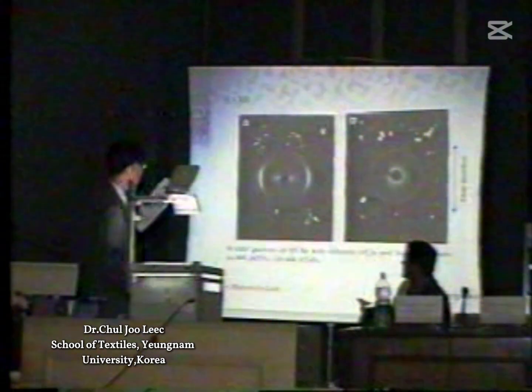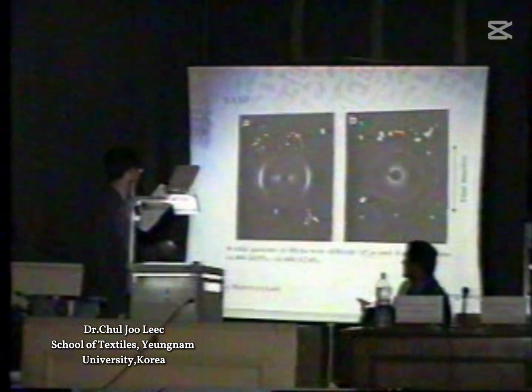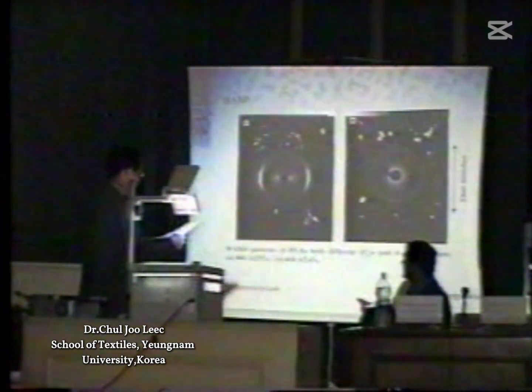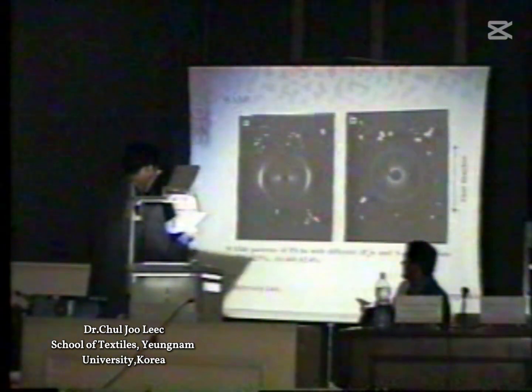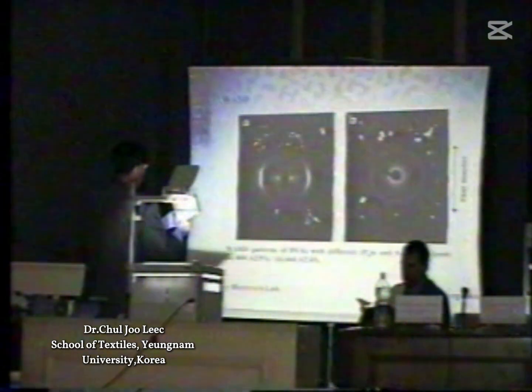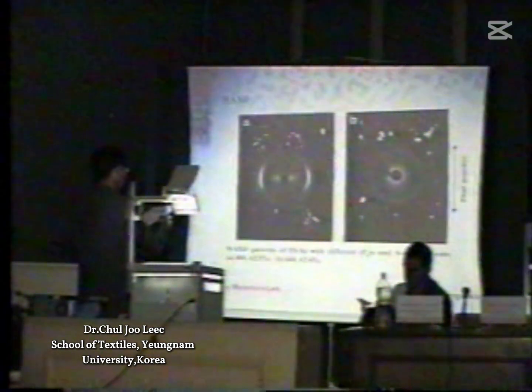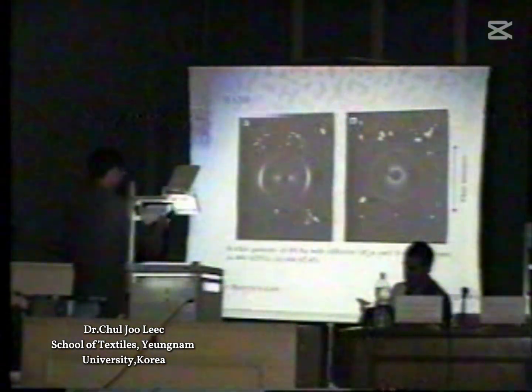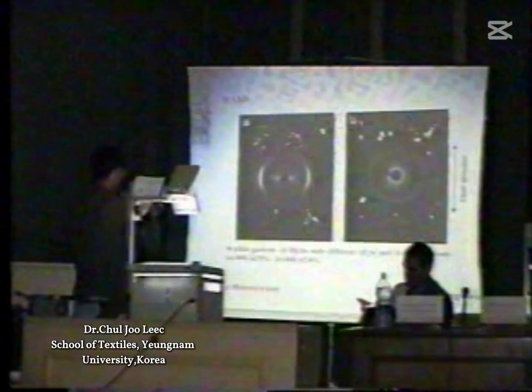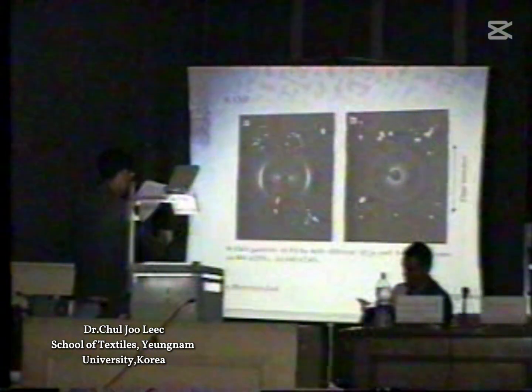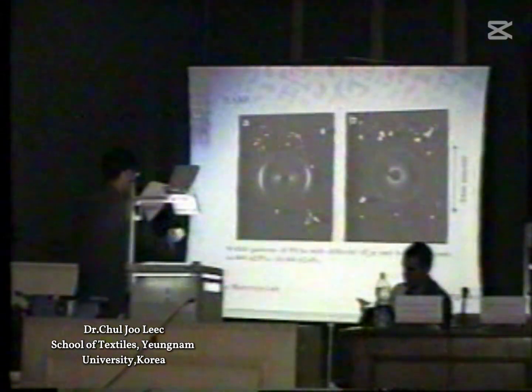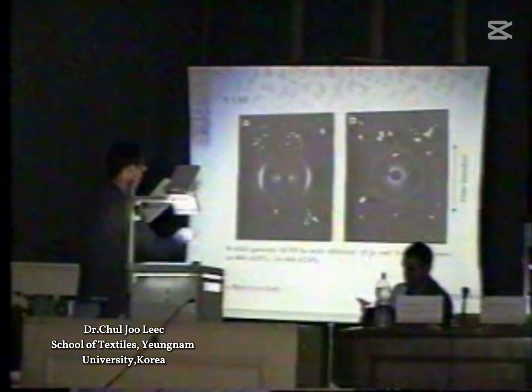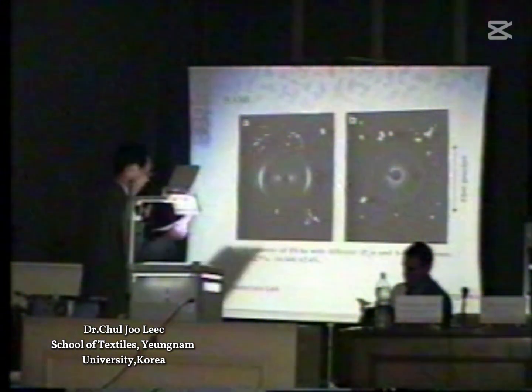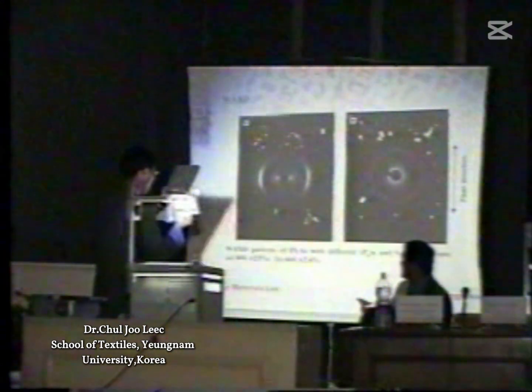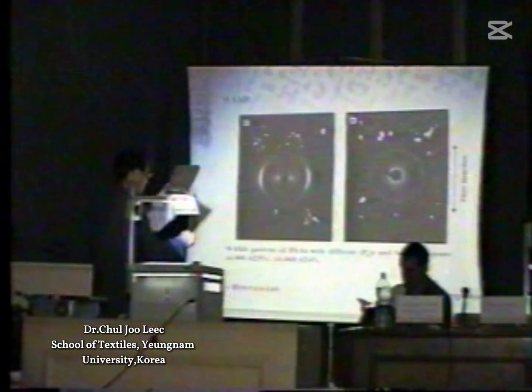Once more, I'm very sorry for the quality of these pictures. These are the wide-angle X-ray scattering patterns of the same sample. From these pictures, we can see the degree of orientation. As you can see, a higher degree of orientation is in the higher molecular weight PVA fibrils. But for the low molecular weight polyvinyl alcohol, we cannot see any evidence of orientation.